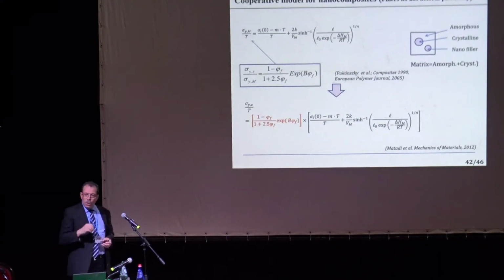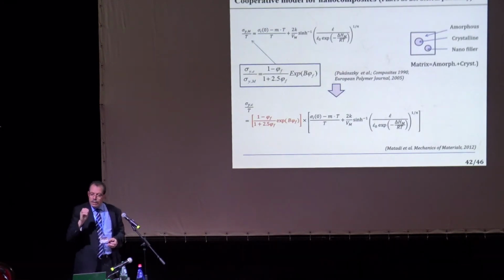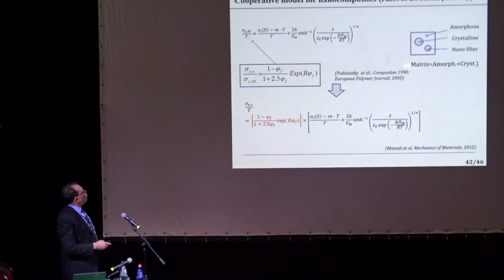Okay. Now, what if the filler does not deform plastically? So I'm not going to calculate activation energy. What happens is you just take the yield of the matrix and modify it because of the fillers. And for the modification, we took this model from these authors, which tells us that the yield of the composite divided by the yield of the matrix is given by this relation.